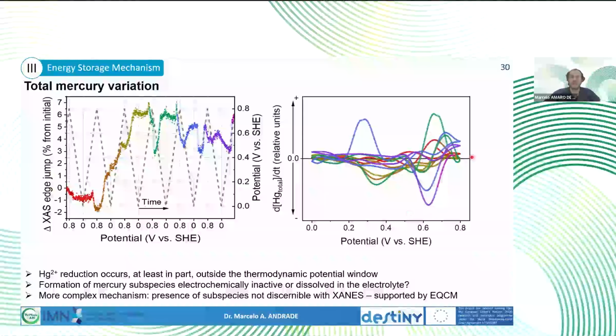So that's the derivative of this curve. And mainly when we had the oxidation peak, we have this sorption-desorption mechanism happening with mercury, and that was seen independently by XAS and by EQCM, by the total mercury variation.